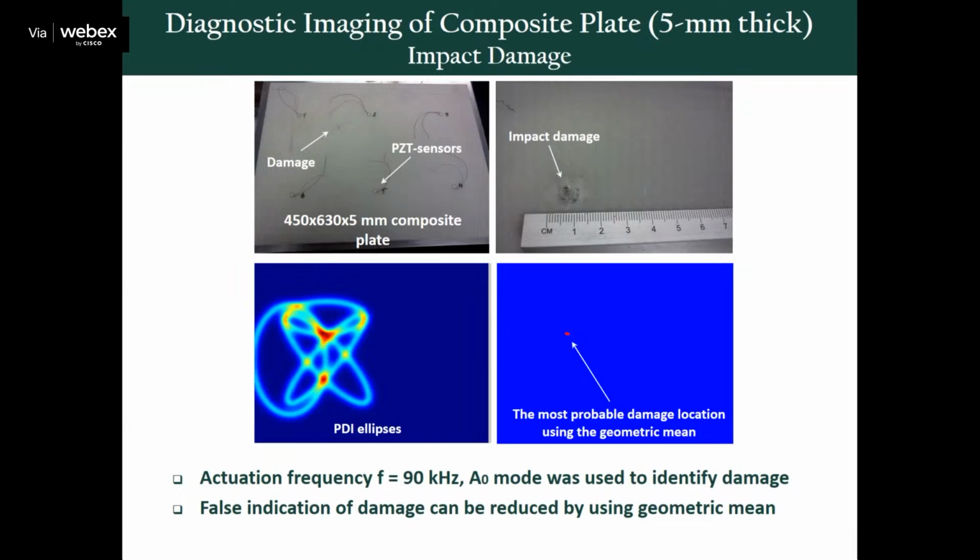Then by adding the ellipse from each pair, because you know the distance between each pair, you can get the most possible defect trajectory on the ellipse by knowing the group velocity in all directions.